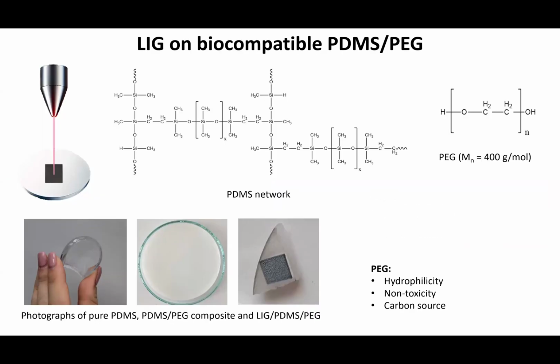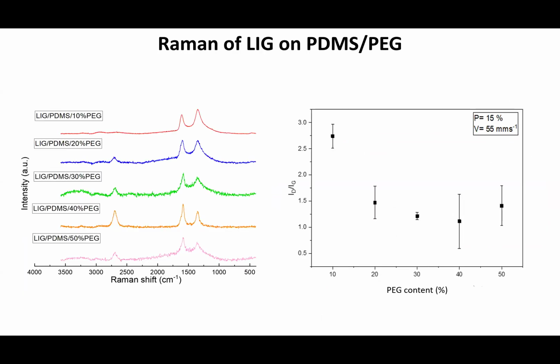One other thing we tried to add to PDMS is PEG, polyethylene glycol, this compound shown on the right here. It's also a carbon-containing compound. And you see, for example, bottom left photographs, PDMS is transparent. If you add PEG, it becomes opaque, and then you can form some kind of graphene on it, shown here in the middle. PEG is hydrophilic, but it's non-toxic, and it's a good carbon source.